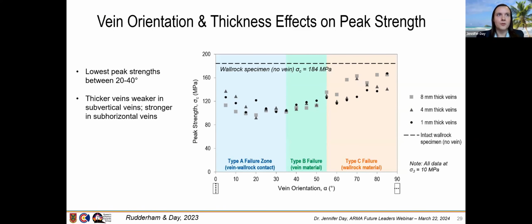A couple of insights from this data: this is again the 10 MPa confining stress. The lowest peak strengths were between vein orientations of 20 degrees and 40 degrees. The thicker veins tended to be weaker when they were oriented subvertically at the lower angles, and stronger in subhorizontal veins. So we had that mode switch, which was an interesting observation that we weren't necessarily expecting.